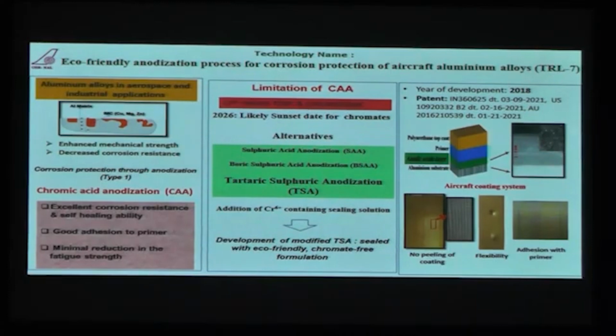But unfortunately, the hexavalent chromium used in chromic acid anodization is highly carcinogenic and toxic, and it has to be phased out at the earliest. According to one of the forecasts, a likely sunset date for hexavalent chromium containing chromic acid anodization is 2026. So the need of the hour is to develop an alternative anodization process which will give performance equivalent to that of the conventional chromic acid anodization.